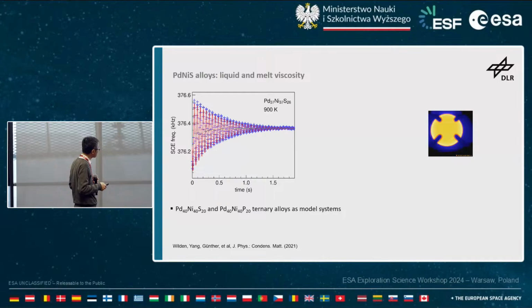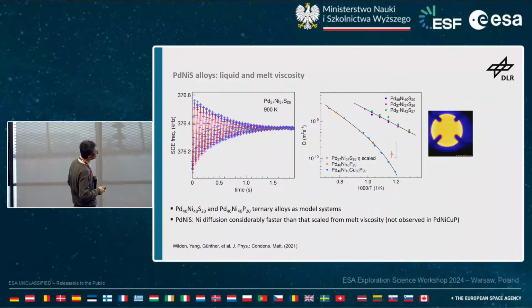We measured at least one of the compositions, which also comes from the previous project. What is surprising is that, as I told you for the previous alloy, the transport coefficient matched the viscosity. Here we see large discrepancies. In this sulfur alloy, the diffusion coefficient is slightly faster compared to the phosphorus alloy, but if you transfer the viscosity into a diffusion coefficient, you see large differences. It is also a surprise for us. It means that either you have a much slower subsystem, palladium for example, or sulfur is connecting something strange. We are currently studying the structure of this.